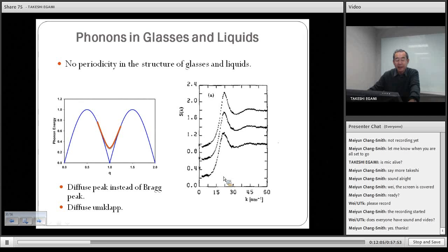Therefore, the phonon frequency comes down to 0. That is if you have a Bragg peak. But here you don't have a Bragg peak, you have a diffuse peak. So the phonon frequency does not come down to 0 at one point, but it comes down over a range of Q. Everything is diffuse. All right. So as a result, you don't see this clear umklapp. Altogether, it looks like it's not a sharp line, but a broad, diffuse line that comes down and then up again. Right? So that's what happens all the time, and that is called roton behavior. That represents this diffuse umklapp.